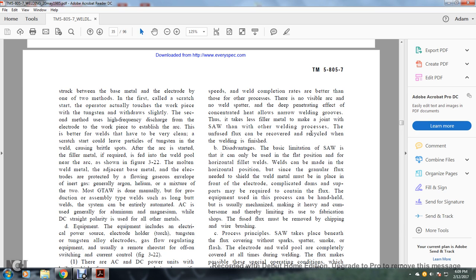Disadvantages: the basic limitation of submerged arc welding is that it can only be used in the flat position or for horizontal fillet welds. Welds can be made in the horizontal position, but are difficult since the granular flux needed to shield the weld metal must be in place. The front of the electrode is complicated with dams, and supports may be required to contain the flux. The equipment used for the process can be handheld or used with a mechanism, making it heavy and cumbersome, therefore limiting it to fabrication in the shop. Fused flux must be removed by chipping and wire brushing.